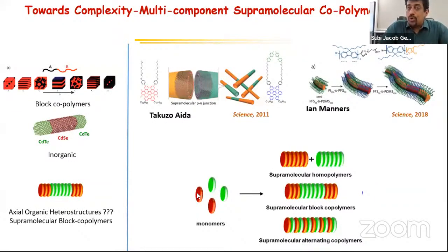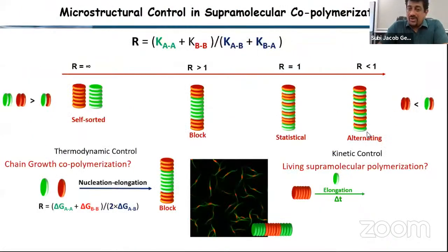Because if you think about two monomers which we combine together, it can either phase separate like a composite, it can form an AB alternating copolymer like polyethylene terephthalate, or it can form this kind of supramolecular block copolymer. So the inorganic heterostructure or organic heterostructure we would like to make will be possible if we can control the supramolecular block copolymer. So again, as I mentioned, always we go back to polymer chemistry, and we know that in polymer chemistry, the chain copolymerization is well understood.